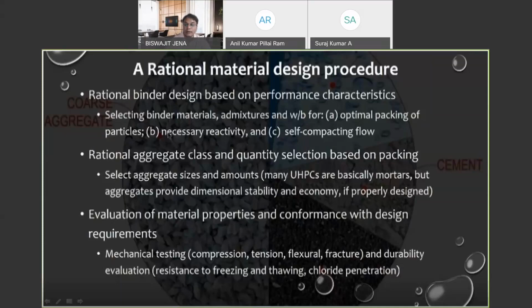And remember, all of these are happening at a water binder ratio between 0.16 and 0.18, which is less than 0.2. So now the challenge is to make sure that all these family of materials act synergistically at that low water cement ratio, which is the first challenge. Then, getting to aggregates again: here I can avoid the aggregates completely and have a self-consolidating ultra high performance concrete mortar. But the problem of not having aggregates is dimensional stability. Your shrinkage is going to be much higher if you don't have the aggregates.